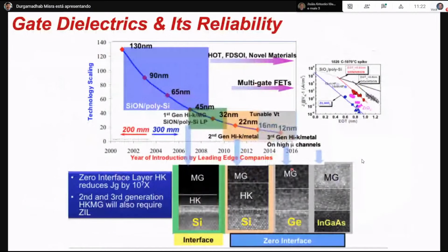So what actually happened when you have 180 nanometer technology, then went to 130 or 90 nanometer technology: at that time the silicon dioxide changed to silicon oxynitride, because nitrogen has the capacity to block any dopant atom diffusion to silicon. The other major problem came around 65 nanometer technology, and slowly trying to go down: the leakage current. The dielectric thickness became 1.2 nanometers. Below 1.2 nanometer, it entered the tunneling region for electron tunneling.